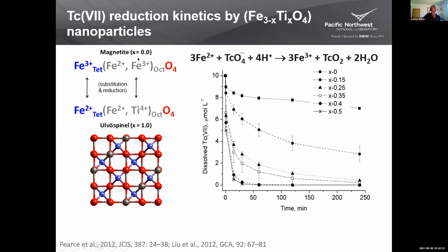And this is magnetite to ulvöspinel, which is the end member titanium-rich species, gives us the chance to really tune that redox potential of the iron mineral phase by changing the amount of titanium in the structure. So as you add in more titanium 4+ to replace the iron 3+, you have to reduce some of the iron 3+ to iron 2+ to maintain charge balance. And so you're increasing the amount of iron 2+ that's present in the solid mineral phase. And as this experiment shows, you're increasing the reactivity with respect to technetium reduction by increasing that solid state iron 2-3 ratio.